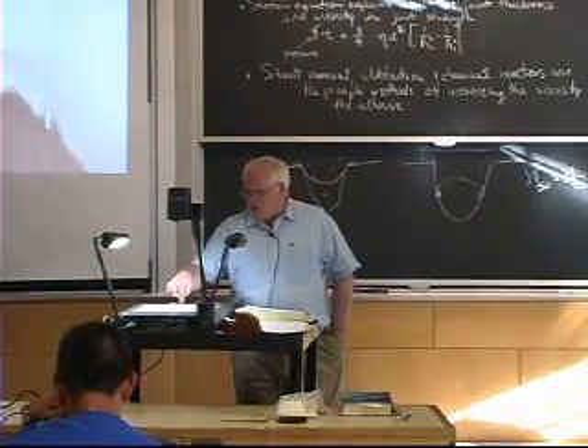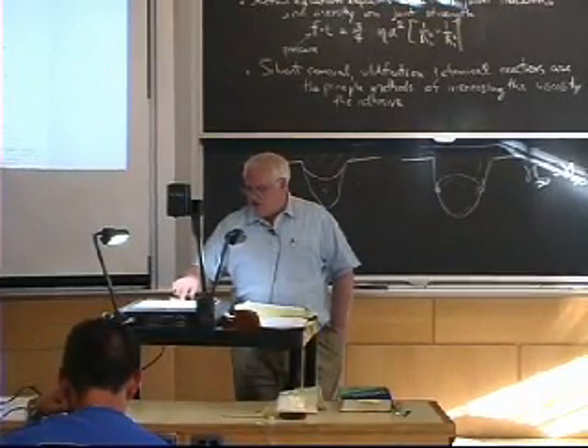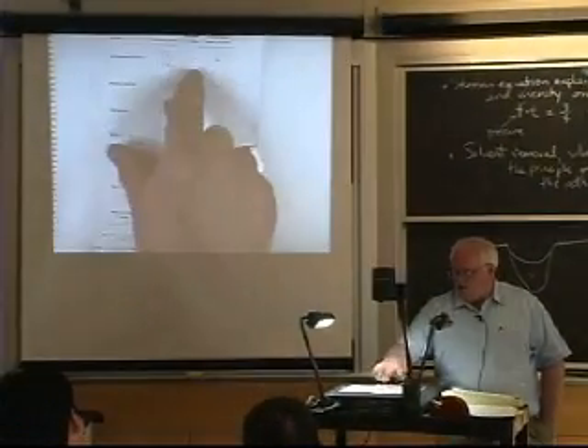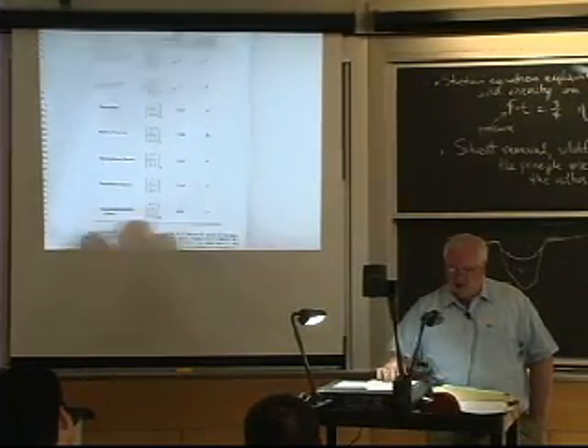And that's what this column is, the static coefficient of friction. You can see the static coefficient of friction, Teflon, we know is very slippery. Polyvinyl chloride's got a static coefficient of 0.9. That's pretty sticky compared to these other things. It all has to do with the surface bonds and the surface energy.